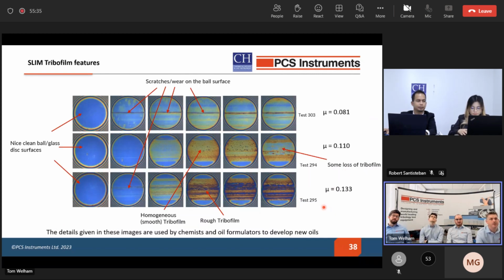So just in a bit more detail, here's 3 oils looking at how the tribofilms have developed, and this just gives an example of what the images look like and the sort of insights we can get into the tribofilm using the MTM SLIM. So we start off here with nice clean surfaces for all 3 tests, and as we progress we see the very different development of these tribofilms. So this one we developed quite a small, quite a thin film. Here we've got a very homogeneous, smooth tribofilm across the whole part of the contact, whereas here we can see how rough and much thicker that tribofilm is, varying as we go across the contact. And these details that are shown in these images give chemists and oil formulators great insight into developing new oils.